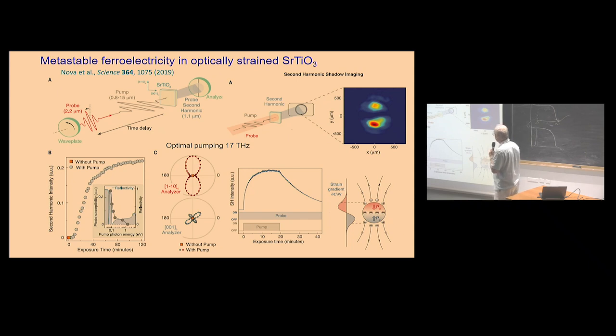But note one point here: they pumped it, let's say, 20 minutes, and the second harmonic generation intensity increased all the time, and then they switched it off, and it remained really half an hour. So it's not a picosecond effect like I mentioned before, but it remains for a long time. They even observed second harmonic generation after 8 hours, which is quite surprising. Yeah, you pump it with femtoseconds and you see it 8 hours later.